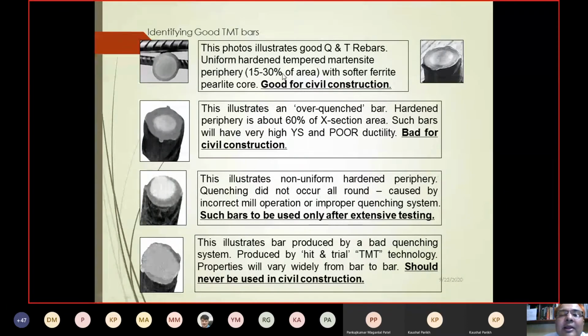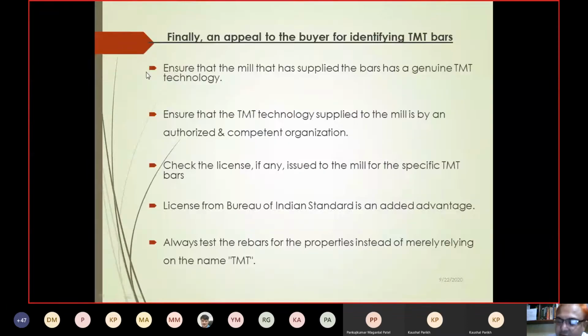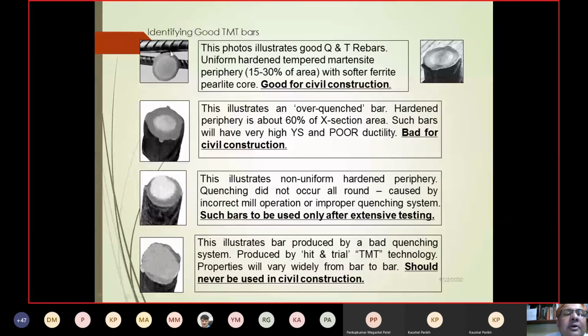Basically, this is the ideal one, good for construction. The periphery is a uniform 15 to 20%, up to 30% of the area. It is a softer ferrite pearlite core. Now, this is also an over-quenched bar. This is not uniform, and this is, we can say, a bad quenching system; we cannot use it.